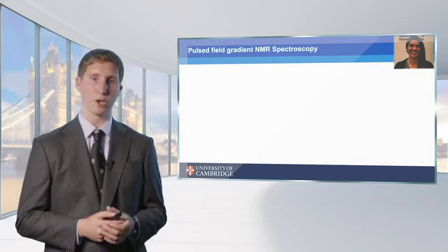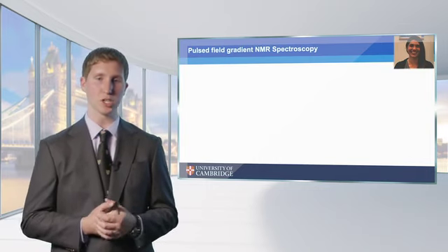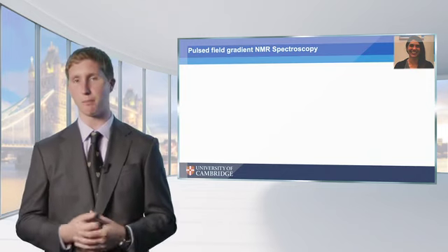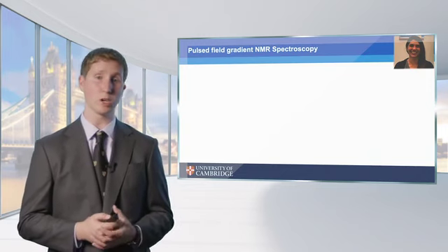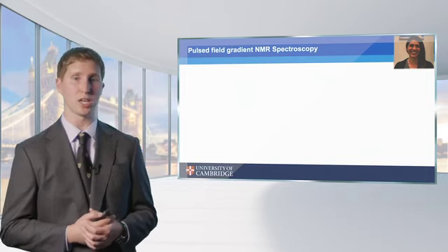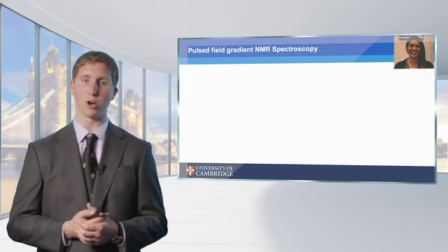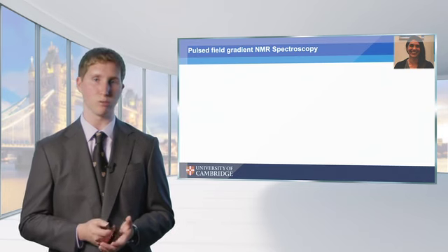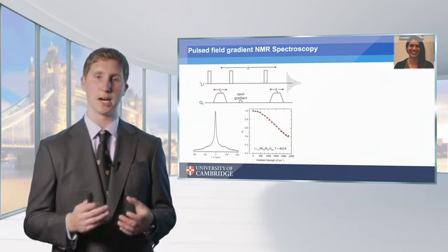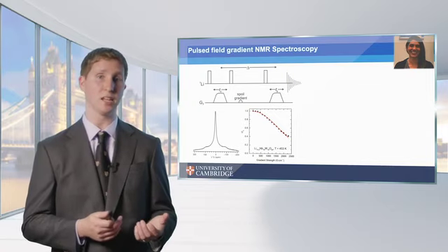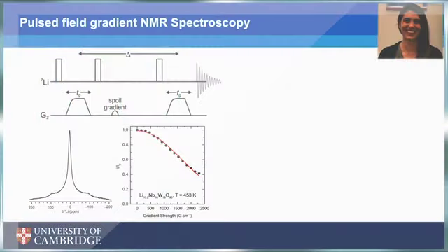And so from that point on, we had this information in hand about the local structure, something about how the lattice responds. And we really wanted to get some information on the dynamics and understand what the kinetics of the lithium are inside of this. And it's challenging in an electrode material because you have electrons and ions carrying charge, whereas in a solid electrolyte, you nominally only have ions carrying charge. So that means in an electrode material, which is a mixed ionic electronic conductor, you really have to find a way to separate these two components. So measuring charge is not necessarily going to be easy to interpret what those charge carriers are.